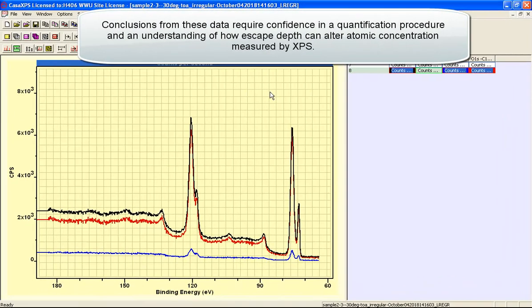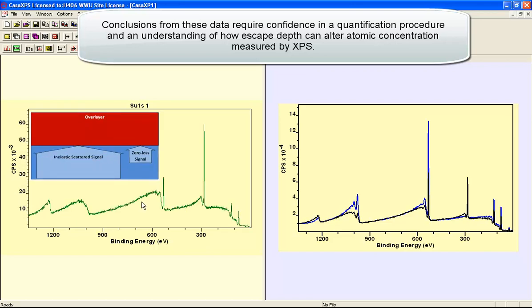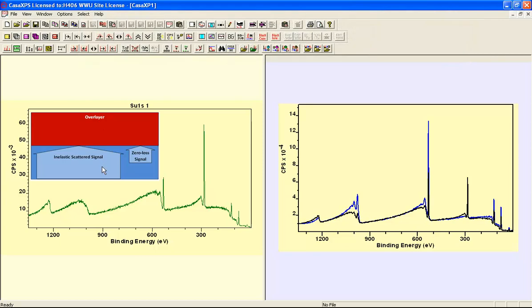These high resolution data have given us an additional insight into these samples compared to the survey measurement. When we looked at the survey measurement, we could conclude that we had aluminium oxide at the surface. We couldn't actually see the aluminium metal as such. We thought there was an overlayer because we have some carbon here. The second component suggested that we had a similar relationship, that we had an overlayer of carbon and we had a substrate that was aluminium oxide. And we could see the shapes in the background were consistent with this type of conclusion.